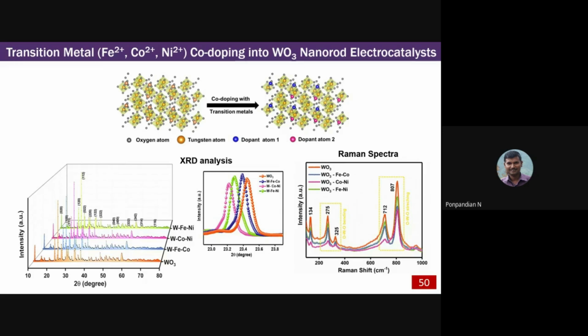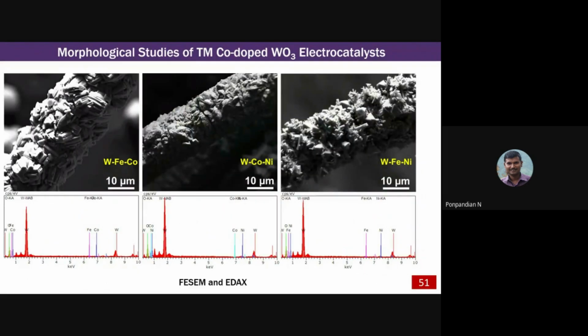You can see some of the structural characterization of this material, the XRD and Raman analysis. Next is the morphological analysis of the iron transition metal co-doped tungsten oxide electrocatalyst. Here are the morphologies. The first one is tungsten oxide with iron cobalt, this is tungsten oxide with cobalt nickel, and the last one is tungsten oxide with iron nickel.